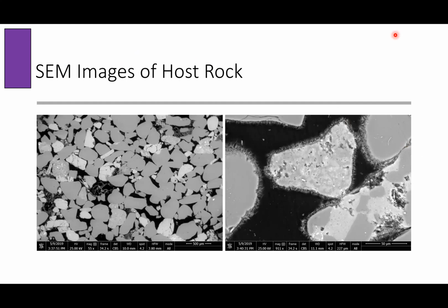So this was kind of interesting to me that you observed that even quartz starts to dissolve in these conditions. What we think is that this quartz dissolution is not the most favorable thermodynamic reaction, but it occurs because of the high pressure. Very high temperatures, right? But did you have any estimates of what the pH is, in situ or in the experiments that you did in collaboration with others? Yeah, in situ it tends to be close to 5 because the brine was trying to reproduce the local brine. We had 3 different brines with different ionic strength, but we were trying to match the brine that is local in this case. So I think that for the quartz, it's a result of the high ionic strength and the high pressure that we have. But what is more prevalent is feldspar. Feldspar is really the first thing that we notice. Feldspar is dissolving in this case, and then the secondary is going to be quartz.